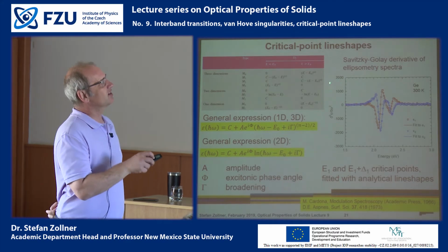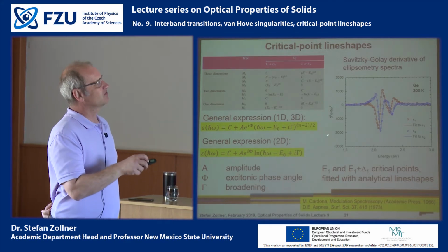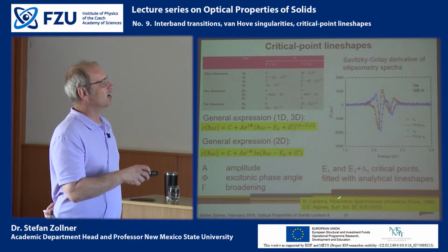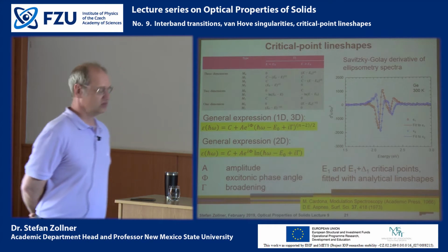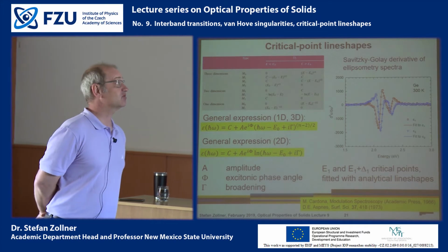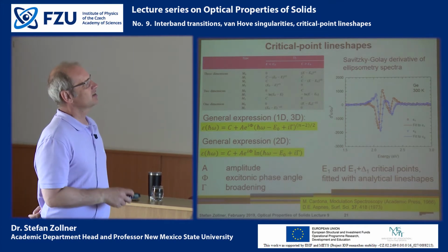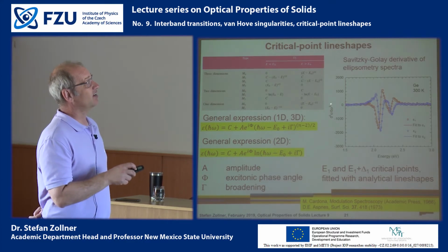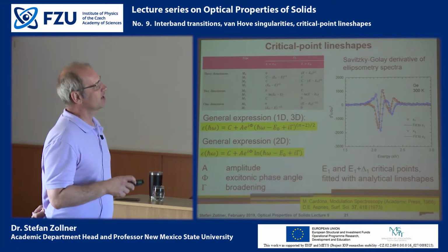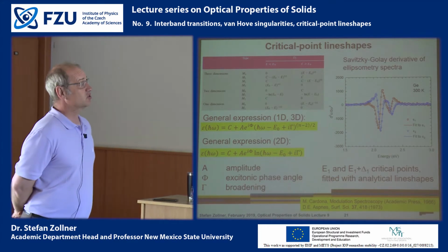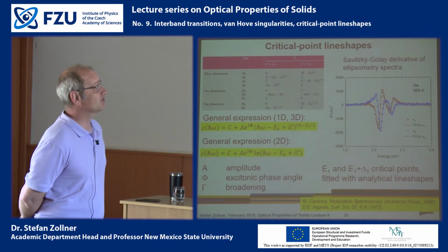So you can actually directly measure the second or third derivative of the dielectric function versus energy, and that is described in some of these older references to modulation spectroscopy. But nowadays, because of the high accuracy of spectroscopic ellipsometry, it is usually more convenient to just do an ellipsometry experiment and then calculate the second derivative rather than doing modulation spectroscopy experiments, which are typically experimentally more involved.